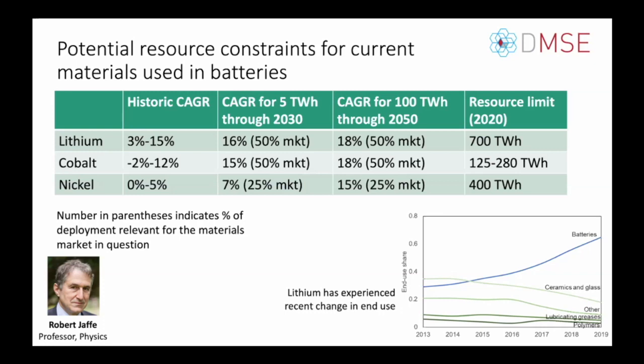This is thinking about both vehicle and grid-based deployment potentially, and this 15% growth rate required is far above the historic CAGR. The other nuance folks may be aware of with nickel is that the vast majority of nickel as currently extracted is not relevant for the EV market, because it's extracted for steel applications and ferronickel. Even growth in nickel has been dominated by expansion of nickel pig iron for stainless steel or ferronickel, with fewer ore discoveries that would lead to battery-grade nickel. The implications there are interesting to consider. We don't mean running out; we mean a change in the nature of the supply of that material and what that means for the supply chains.